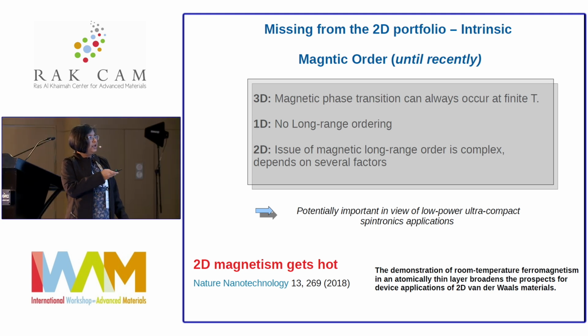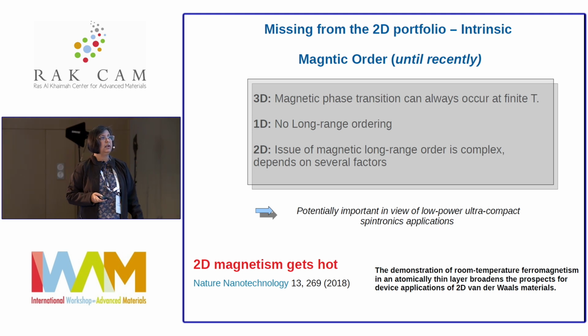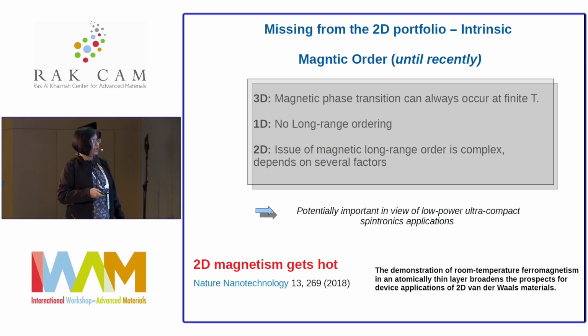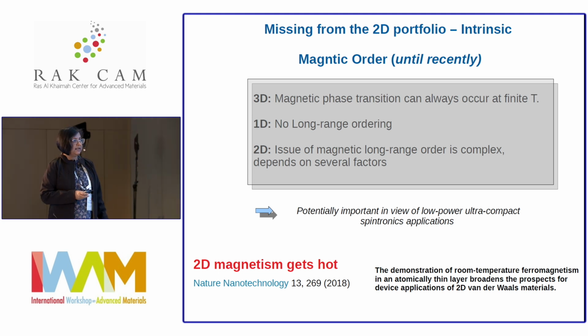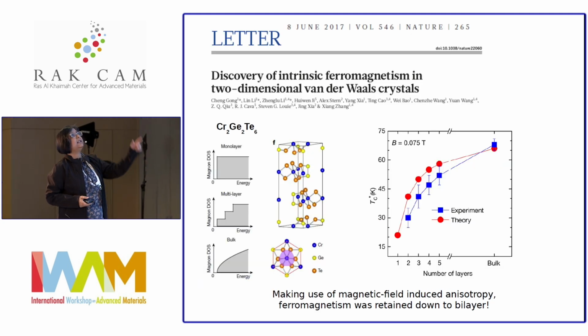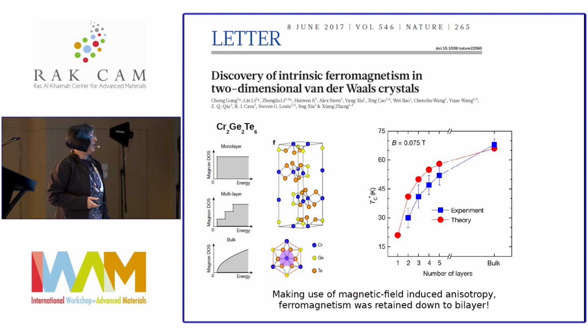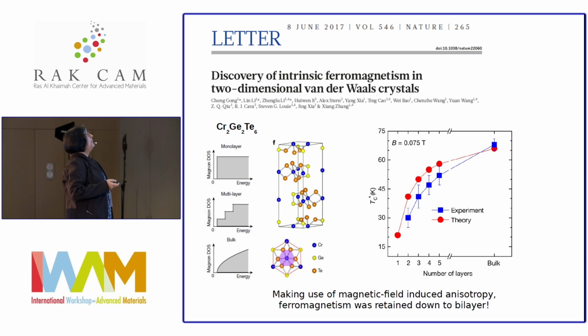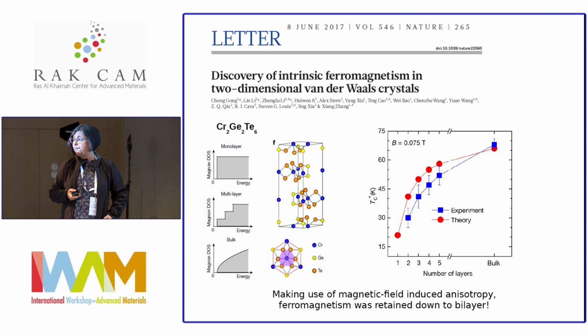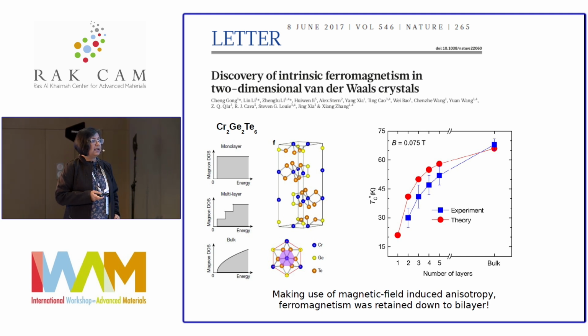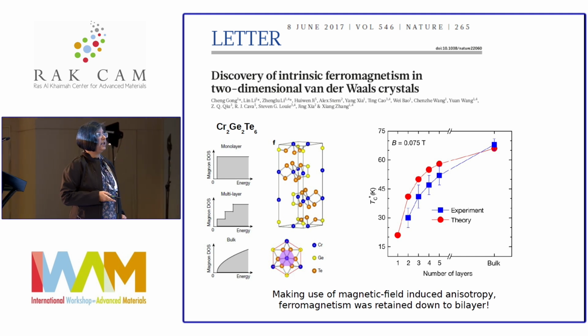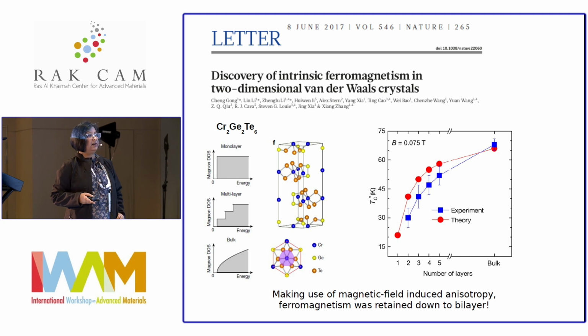And that's actually of potential importance in view of low-power, ultra-compact spintronics applications. A few years back, that's basically the story in Nature Nanotechnology, which says 2D magnetism gets hot. This started with two back-to-back Nature papers, where, taking the compound chromium germanium tellurium, by application of a moderate amount of magnetic field, even at the bilayer limit, this material is found to be a ferromagnet with a TC of the order of 20 Kelvin.